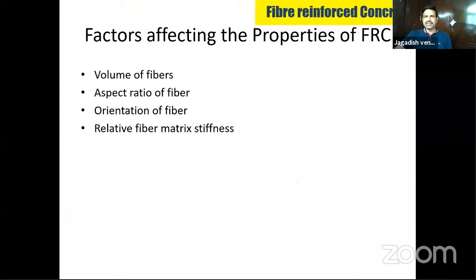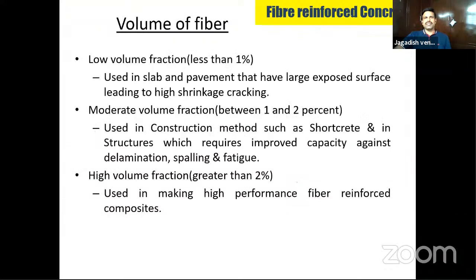But what are the factors that affect the properties of FRC? We should know. One is the volume of fibers. How much volume do you use: low volume, moderate volume, or high volume? It affects the properties, and so do the aspect ratio and orientation. Coming to the volume of fibers, if you're using less than 1% fibers, we call it a low volume fraction. Usually we use it for horizontal applications, particularly slabs, pavements and horizontal exposed surfaces.